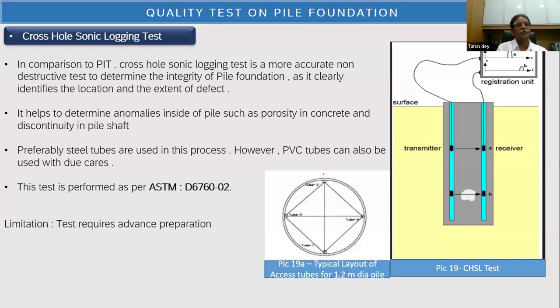Now, there's another test called cross-hole sonic logging. This is a further improved one, where you can see the defects, the location of the defects, and the extent of the defect in a better way. In this cross-hole sonic logging test, we need to insert 4 pipes in the pile before you cast. So this is one of the key limitations. This requires advanced preparation. You need to identify in advance which piles you will do the cross-hole on. The quantum could be 10% to 20% for any site, but it requires advanced preparation. And these pipes could be of steel or PVC.